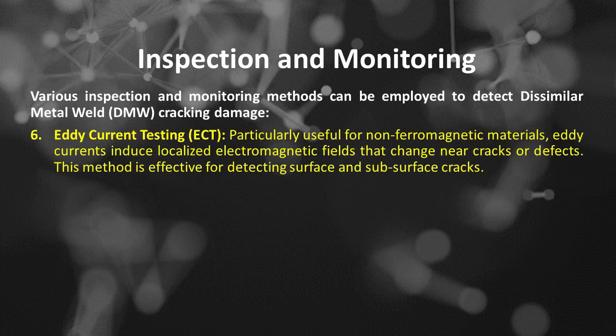Number 6 is eddy current testing, or ECT. Particularly useful for non-ferromagnetic materials, eddy currents induce localized electromagnetic fields that change near cracks or defects. This method is effective for detecting surface and subsurface cracks.